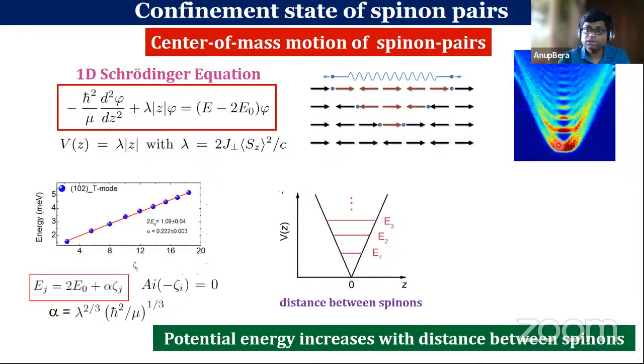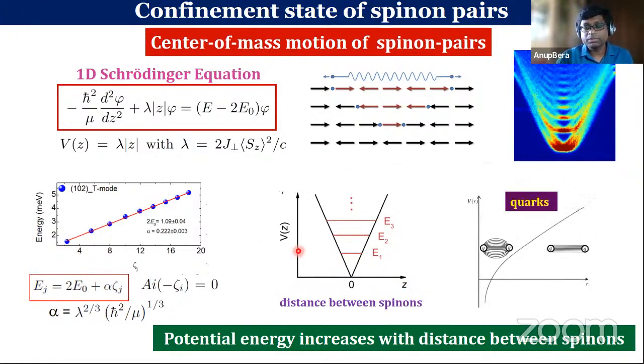And if I plot the eigenenergies of these states as a function of the negative zeros of the Airy function, it shows a linear behavior. So it shows that there is a linear potential, which is very much like quark confinement. So it proves that we see quark-like confinement in a condensed matter system.